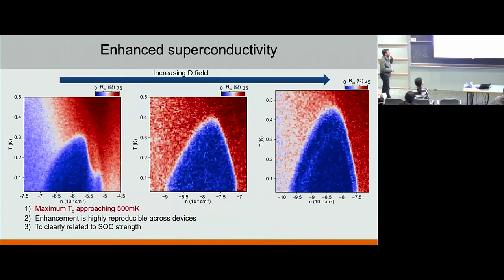Now, if you go one step further, I promised you some higher Tcs, or at least higher than in the case of vanilla bilayer graphene. The idea is that the more you polarize, the more your Tc is increased, up to some point. And in the original work we had a few different samples where we could at least make a claim that the Tc is related to the spin-orbit strength.